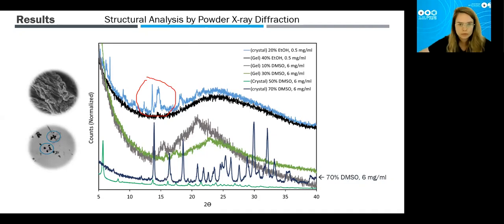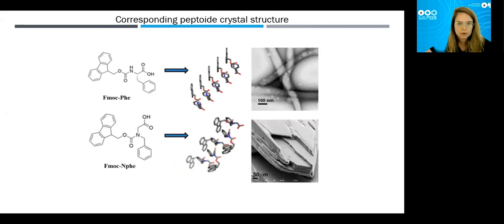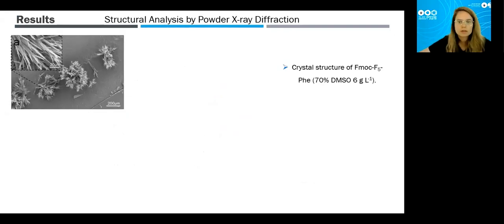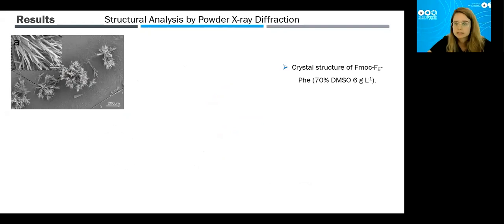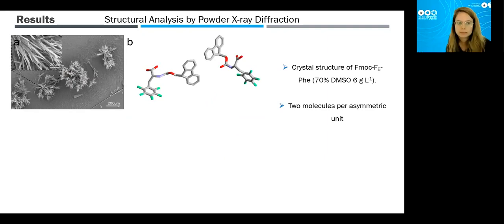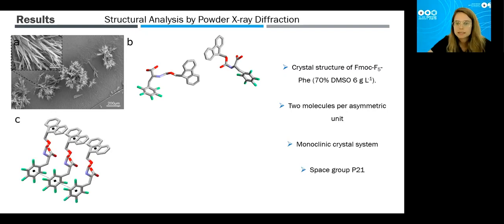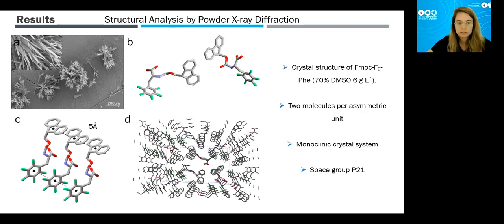These results were very exciting because no one had previously solved this crystal structure. Researchers had designed the corresponding peptoids — where the side chain is shifted from the alpha carbon to the nitrogen — and only the peptoid crystal structure was known, not the peptide. Our strategy allowed us to overcome this challenge and resolve for the first time the crystal structure of this building block. We obtained needle-like crystals, two molecules per asymmetric unit, a monoclinic crystal system with space group P2_1, stabilized by pi-pi aromatic interactions between the phenyl group and between the Fmoc groups.